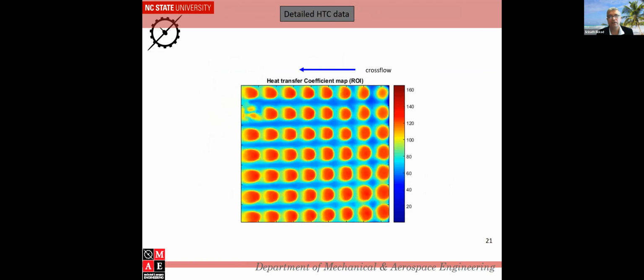So this is how a heat transfer coefficient map looks for liquid crystal data for an impingement cooling system. You can see all the red spots are where the jets are hitting, and you can see the heat transfer coefficients. And this is where we do our calibration. That's why you don't see the data here, because the calibration curve is got from that point.